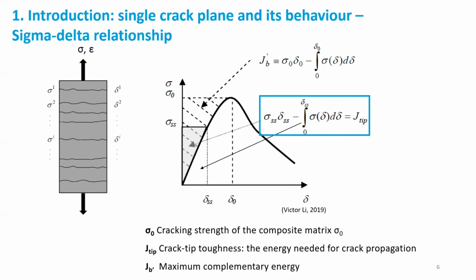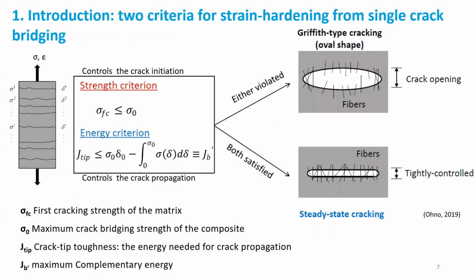Another very important term is the complementary energy, which corresponds to the left part of this equation. The maximum complementary energy is calculated using the crack bridging sigma-delta curve. To ensure the energy balance, we have two criteria. The first one is the strength criterion, which controls the crack initiation, and the second one is the energy criterion, which controls the crack propagation. When both criteria are met, we can have steady-state cracking, and finally we'll have strain hardening behavior of the composite.